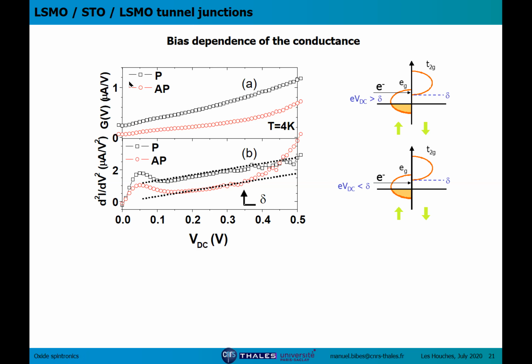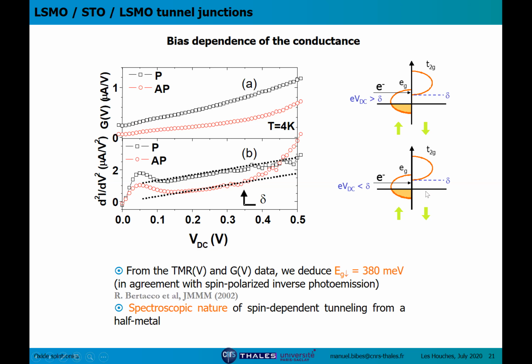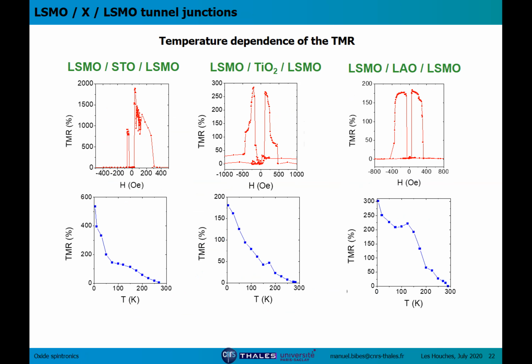So you can do conductance and differential conductance measurements to detect the onset of tunneling into this spin down subband. So we can measure the spin minority gap in LSMO, and we found a number of about 380 millivolts, consistent with measurements done by Riccardo Bertacco using spin polarized inverse photoemission. Just like when you do STM or scanning tunneling spectroscopy, you can use the spectroscopic nature of tunneling to gain insight into the electronic structure of your materials, and here it can be done in a spin-dependent way. So this was about the bias dependence.